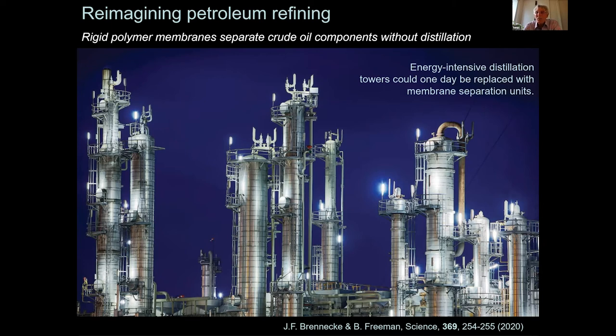I thought that this was not too difficult with the kind of membrane that people are able to do right now, but I was wrong. It's a real tough problem, because you need pores in a range going from, let's say, 3 angstroms to several nanometers for the different molecules that you have. And the point with polymer membranes is that in the myriad of molecules that you find in crude oil, there is always a good solvent for the type of polymer that you used for the membrane. Of course, you might say you can do the same thing with ceramic membranes, but that's even more difficult as far as material science is concerned.